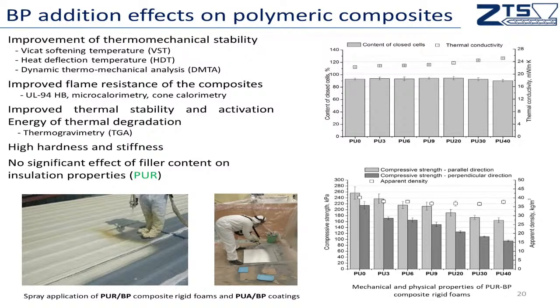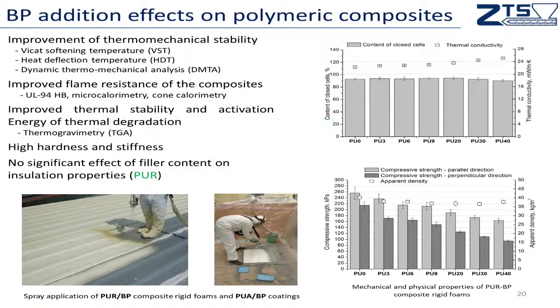We can reduce more than 40 or even 70% of the petrochemical materials and make the polyurethane spray foams much more sustainable and environmentally friendly. So this is really a big achievement, even if we see that the compressive strength of the material is a little bit lowered. Those properties are still at an acceptable level, and we must remember that each time we replace 10 or 40% of the polymer in the composites by waste material, we achieve materials that are characterized by much less environmental impact and lower carbon footprint.